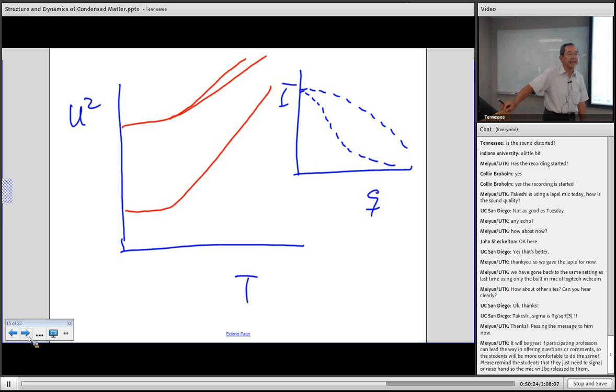And you have defects. So all these defects and this local mixing and this kind of disorder, randomness, produce an apparent U, which is not due to phonons. Right? So there are two kinds of this Debye factor U. One is phonon, which you can calculate. The other one depends on the sample imperfection, disorder in the system.